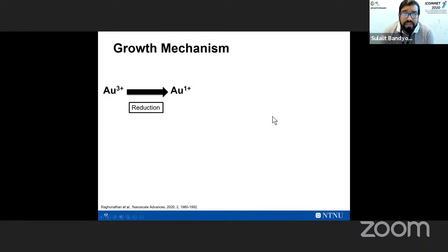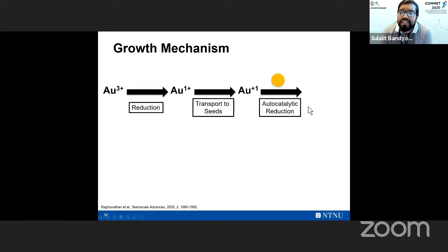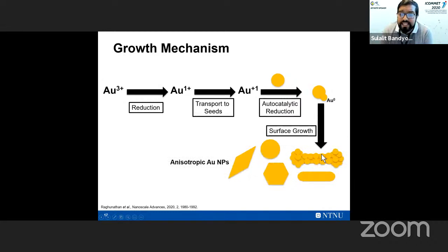Then further on, I would show you how these particles grow. This is our presumption, in the sense that there is first a reduction step. The hypothesis is that this is then transported to the seed surface. And on the seed, we have an autocatalytic reaction, which results in the formation of these different structures. And then we have a surface growth that results in these nice shapes. So there are two important steps that one should take into consideration: the surface growth and the reduction process, which are competing to form these different shapes.